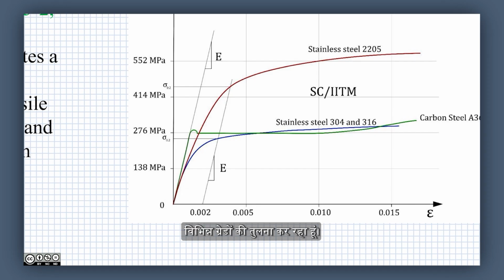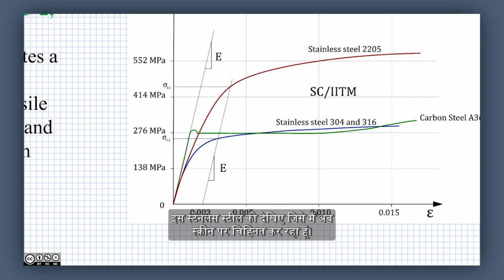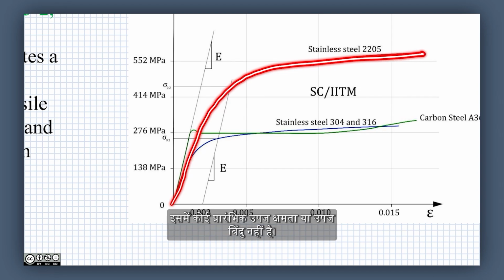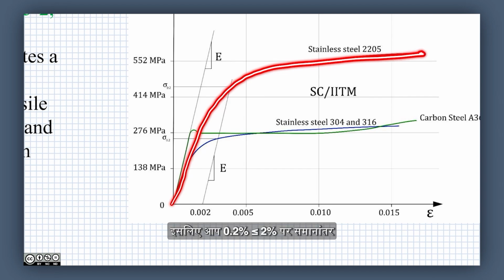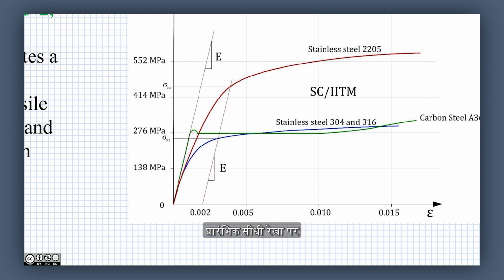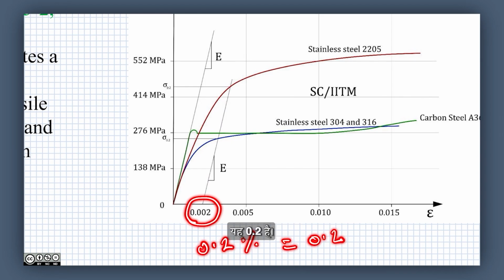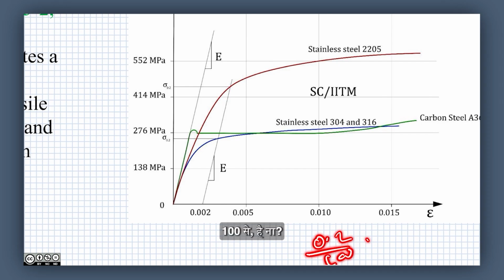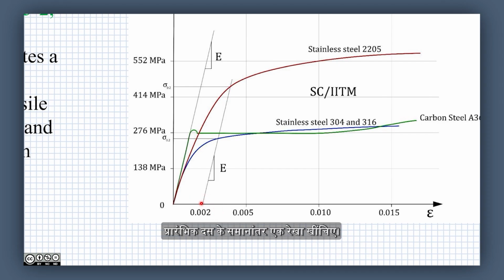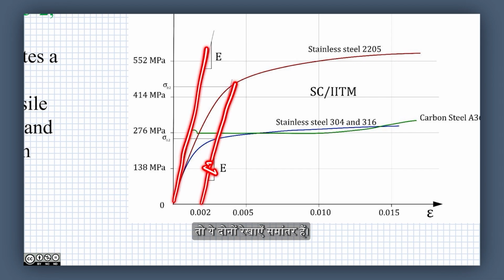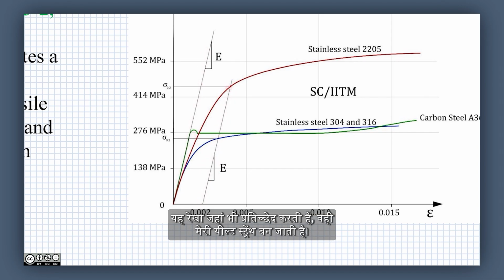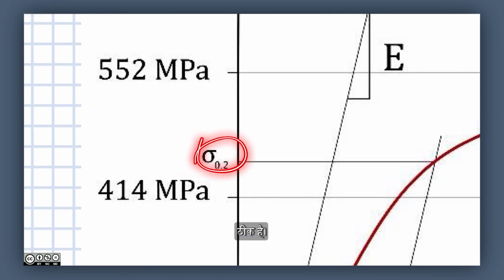I am just comparing different grades of steel for our information. Look at the stainless steel, which I am now marking on the screen. Okay. There is no initial yield strength or yield point. Therefore, you draw a tangent to the initial straight line parallel at 0.2%. 0.2 by 100, is it not? Therefore, 0.002. Draw a line parallel to the initial tangent. These two lines are parallel. Wherever this line is intersecting, that becomes my yield strength. Okay, that becomes a yield strength.